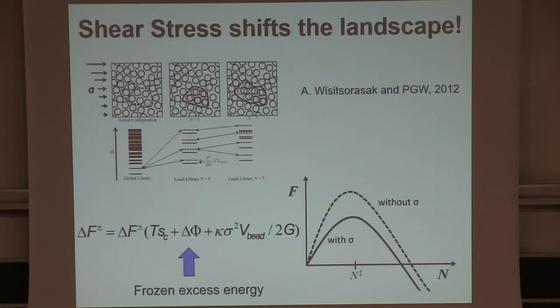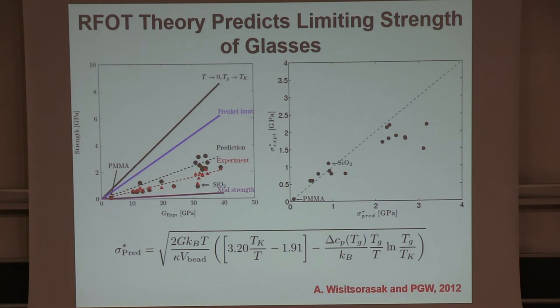Also, we've heard about stress and elasticity quite a lot here. Stress is another way of changing the energy of the region that needs to nucleate. If it can nucleate to a region that has no stress, then that energy gets given up. That makes it easier to make this transition. And one can calculate from that when the barrier would go to zero, and that tells you about the strength of glasses. So I guess I'll end there, but to say that this theory in which you put the instantons back into mode coupling theory is a very rich kind of theory.